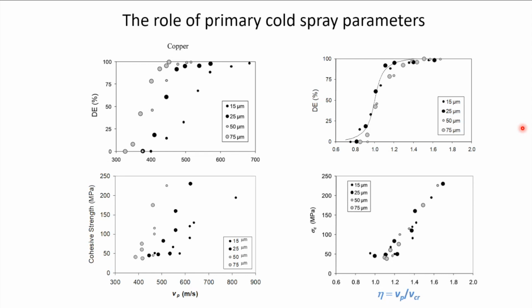That was quite interesting, because then instead of dealing with too many different variables, you could separate the effect of material properties from the process parameters and then bring everything into one single parameter, which is called eta. I think eta is now being used for research, but probably not widely. But I think it's a very good rule of thumb to see where you're at in the cold spray space.